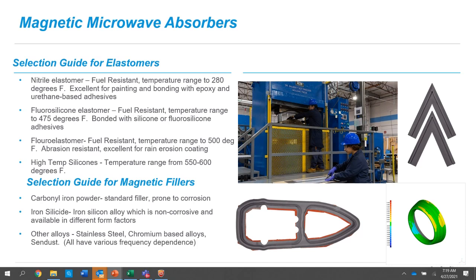Those pictures there, that's a large compression molding press. And then you can see some of the detailed parts. That lower right picture is actually a Viton edge lip. The Viton was chosen for its high temperature and the abrasion resistance that it has. And it was some modeling we did to manufacture that part. That lower left is a gasket, a dual blade seal gasket, and then some unique shape parts. So we can mold specific shapes with these materials to meet your exact requirements.